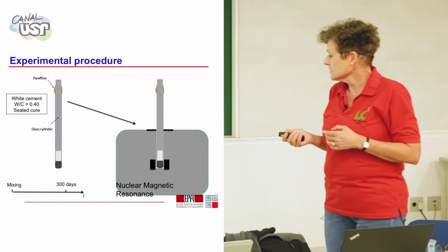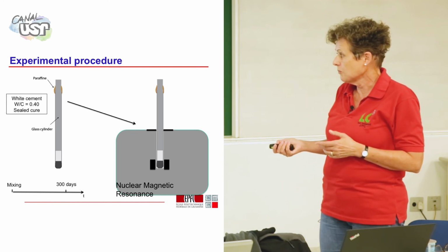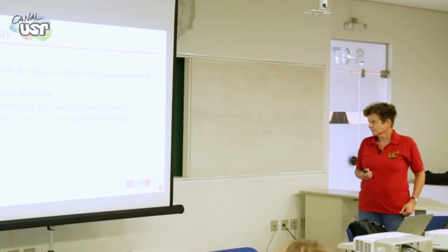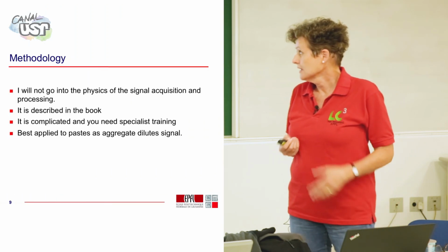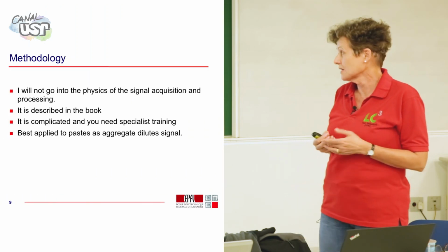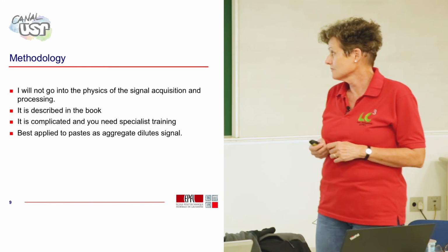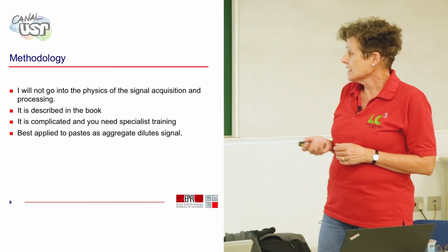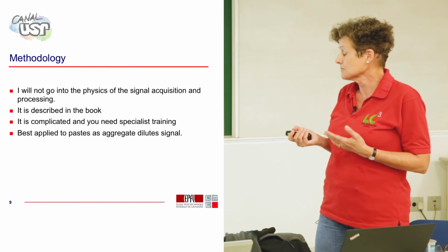And you can keep measuring this sample as long as you like. We've measured up to 300 days, up to about a year, but you could go on longer if you wanted to. So I'm not going to go into the physics of the signal acquisition. It's described in the book. It is quite complicated, and you do need to work with somebody who understands it to understand how to do it. And as with many of these techniques, it's best applied to paste because aggregate dilutes the signal.